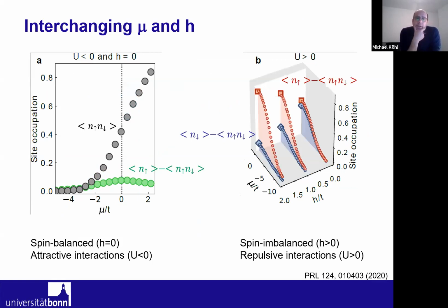And what we do in the experiment, as I showed you in one of the very first slides, is we measure the density as a function of position in the harmonic trap. And if we assume that our sample is well thermalized, we can assume that we have a constant chemical potential throughout the trap. But this means locally the chemical potential changes if we believe in a local density approximation. So this means by extracting the densities from certain points of the picture, we can extract densities corresponding to different values of the chemical potential. And that is shown in this left graph here. So you see in gray the density of the doubly occupied sites for different values of the local chemical potential. And in green, you see the density of the singly occupied sites, so spin up minus doubles.